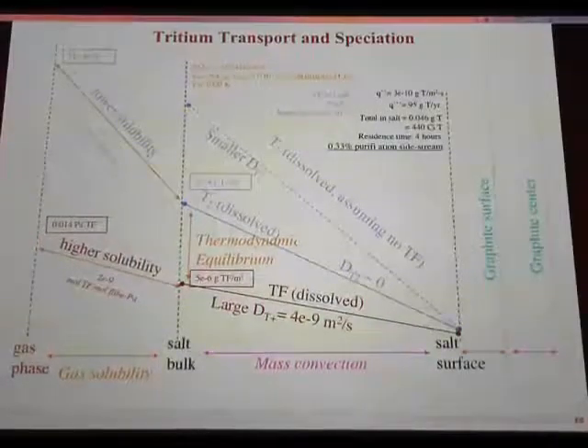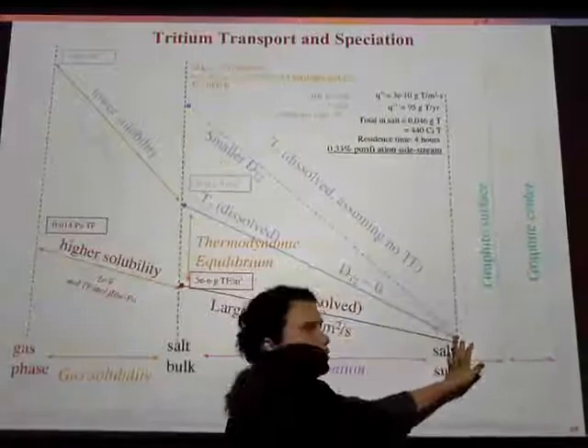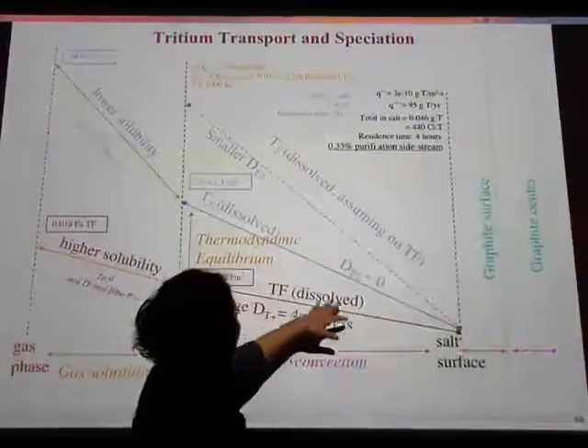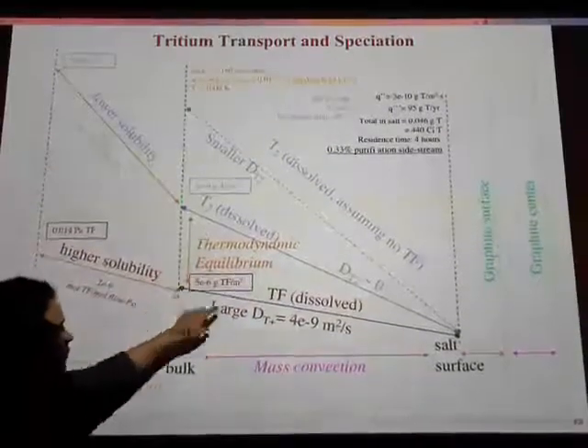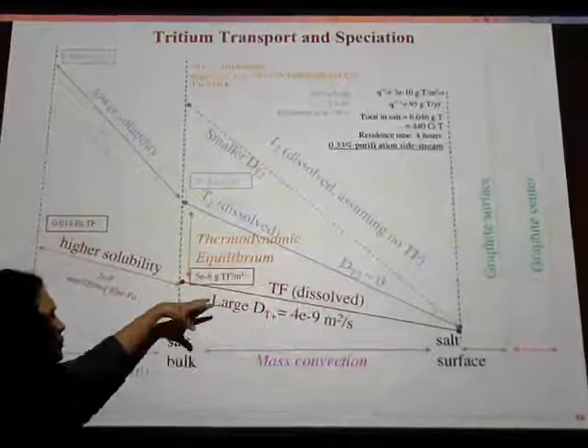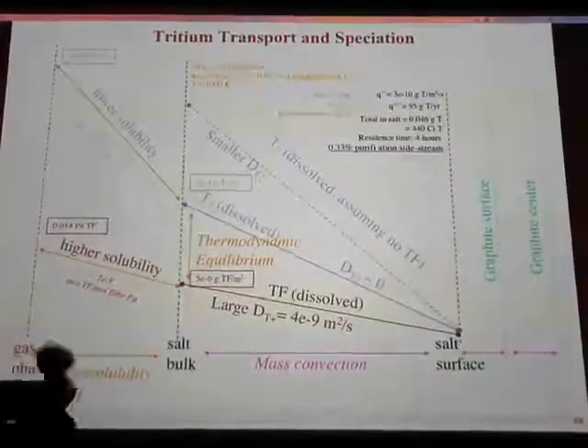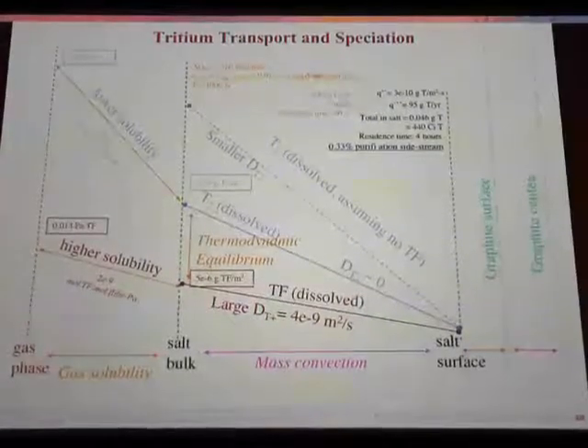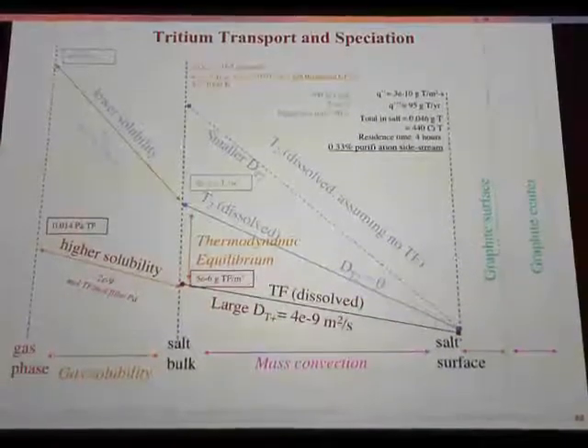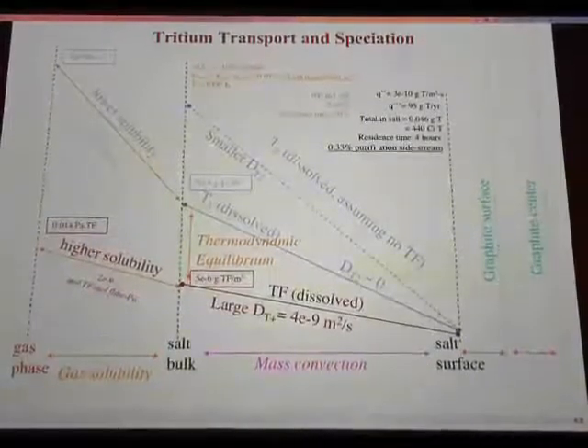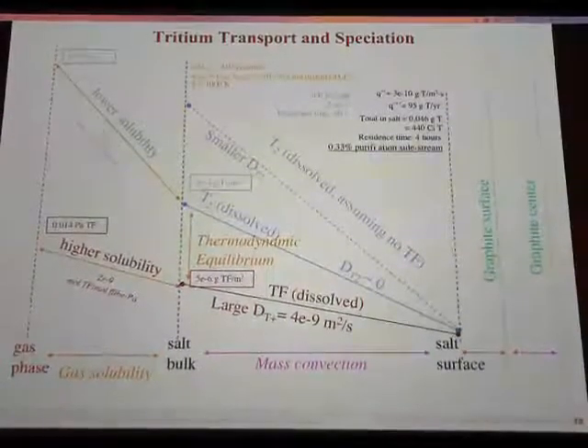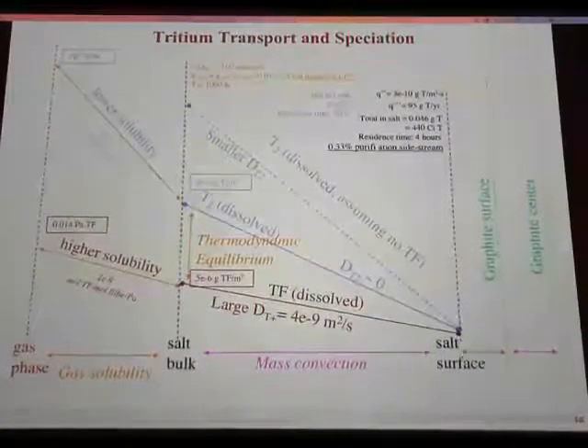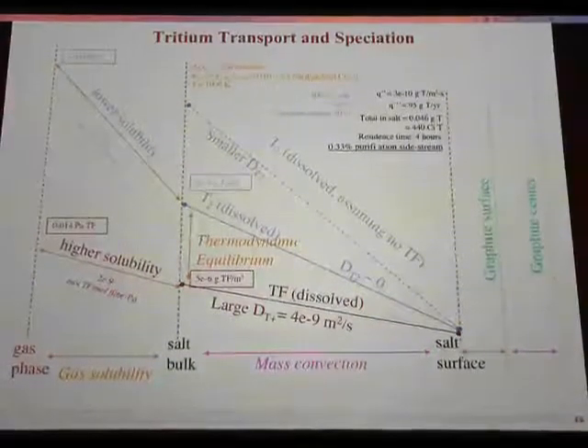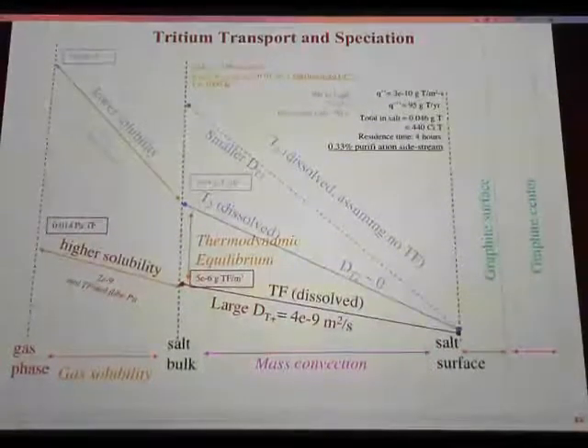So if you assume that you have 0 concentration at the salt surface, and you know the flux that needs to go into your fuel pebble, and you know the diffusion coefficient and the mass transfer coefficient, then you can calculate what the concentration of tritium needs to be in the bulk. Now what's interesting about tritium is that tritium can take many chemical forms. It could be a molecule, it could be an ion, it could be an atom, it could be an anion, but we won't talk about anions. So to simplify problems here, we're just going to talk about molecules and cations. So it can be T plus or T2, let's say.